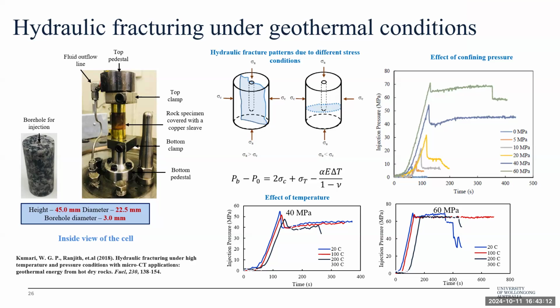Okay, next, this is the next component of the talk, hydraulic fracturing of granite rocks at geothermal conditions. In this test, we considered cylindrical rock samples, and we control the stress state to make sure we have a vertical fracture along the wellbore, and we created the wellbore using a 3 millimeter drill bit. And here you can see the generated